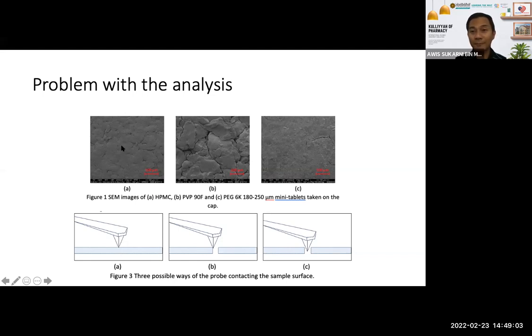It means the actual, accurate reading. The second possible way is that the probe lands at the edge of the sample, for example at the edge of this area. When this happens, it might show you an inaccurate reading. The third one is that it lands in the gap between the sample, for example here. When this happens, the probe lowers down until a certain limit, and after that it heats up in this area. Heating up from 25 to 250 degrees, if it doesn't notice anything, it will just record it as 250 degrees or 0 degrees.